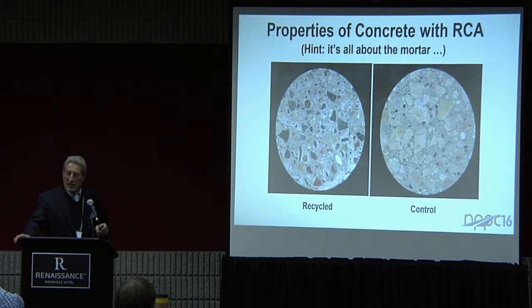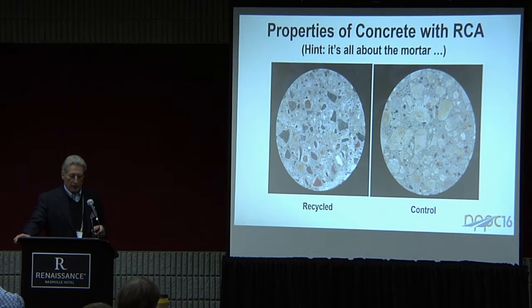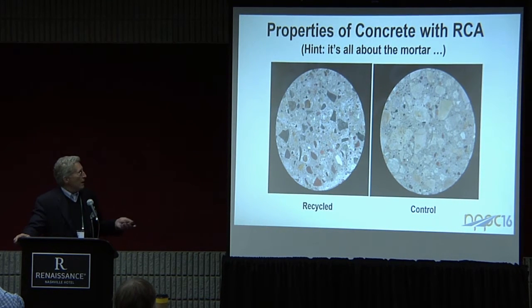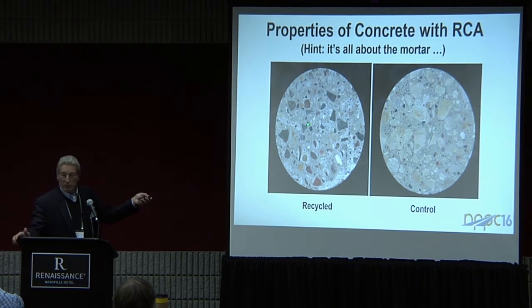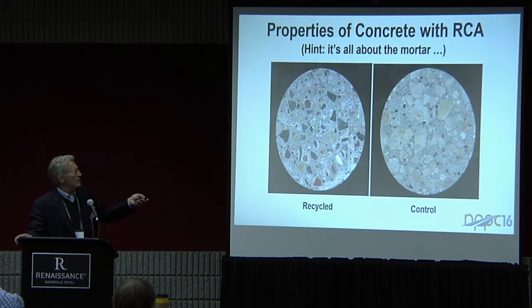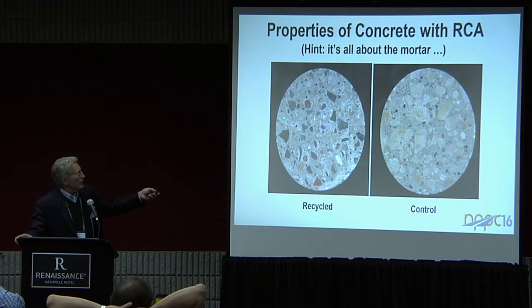If we look at the properties of concrete that's made using crushed concrete aggregate or recycled concrete aggregate, as the slide says, it's all about the mortar. Here's a recycled mix. This is from one of the jobs in Minnesota. It might even have been the job we were looking at there. No, it's not. This is from one of the ones on Interstate 90. But anyway, you can see smaller particle size. This was crushed down to 3/4 minus. Again, they had a slight D-cracking concern, so they crushed it down to 3/4 minus. This one, you can see larger particles here. If you look at this one, you can also see mortar. Some of it's kind of dark colored, and some of it's kind of lighter colored.